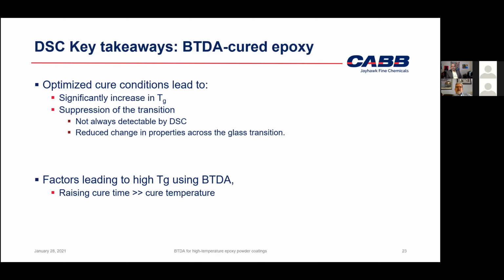There is precedent with a few powder coating chemistries where further advancement of Tg, further network development, happens in service, especially for high heat applications where something is going to have relatively continuous high heat for long periods of time. And the coating is pretty darn good when it gets into the field, when first put into service, but within hours, it's significantly better.